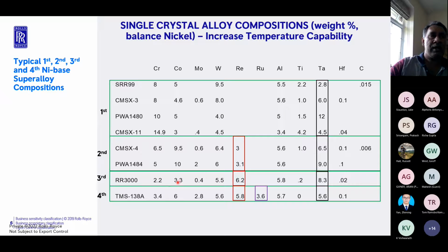So one of the ways of overcoming the drawbacks of third generation alloys was the creation of fourth generation alloys. So fourth generation alloys, again, the major difference is now the addition of ruthenium. And one of the main reasons for adding ruthenium is you can slightly decrease the amount of rhenium, but even for that amount of rhenium, the presence of ruthenium stabilizes the alloy.